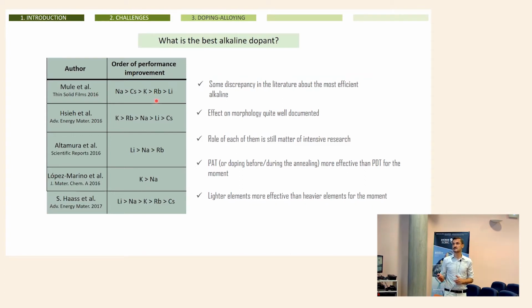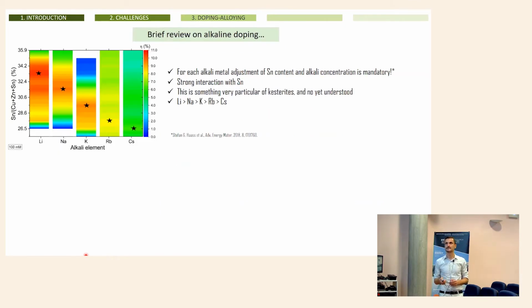We thought that the same would happen with kesterite, and to some extent, yes, but several groups working on that more or less at the same time, when this alkaline doping started to be a hot topic on kesterite, reported differences. For some of them, sodium was the best alkaline to dope, for some other potassium, for some other lithium, and so on and so on. There was a discrepancy in this scientific community about which alkaline is the best for kesterite. And in one of the European projects, we discovered that this is because alkalines interact with tin.